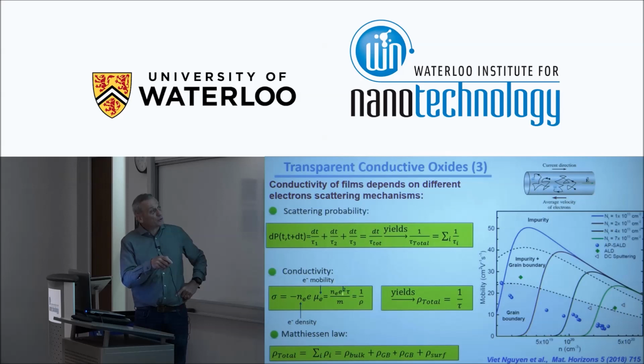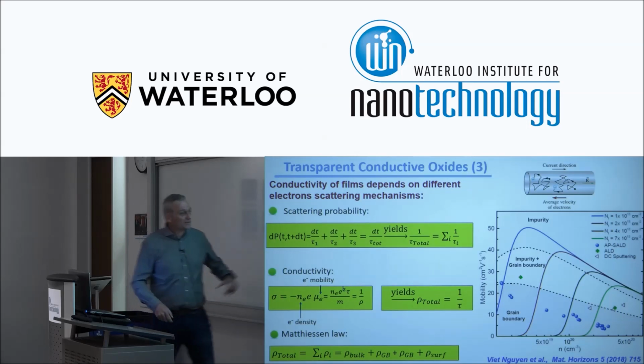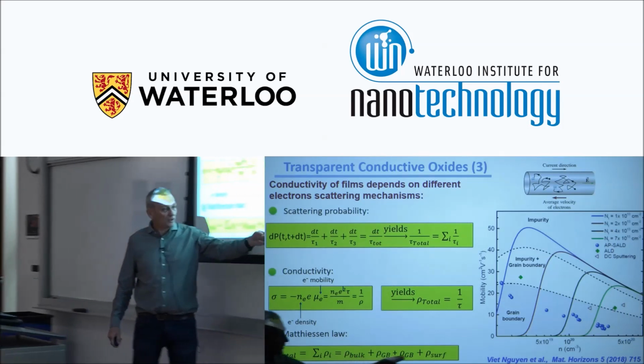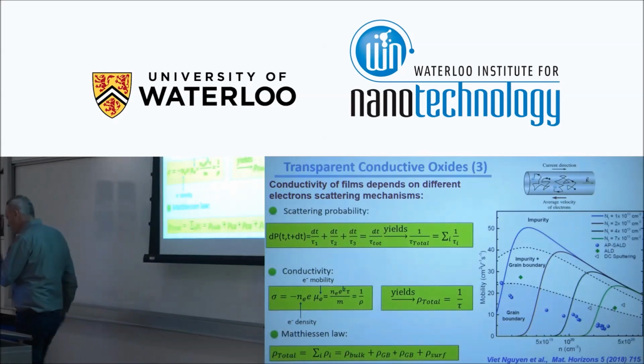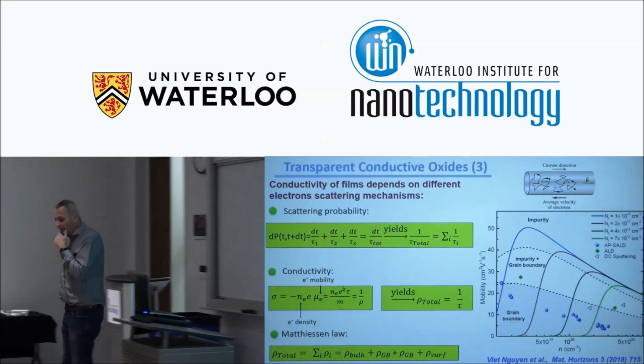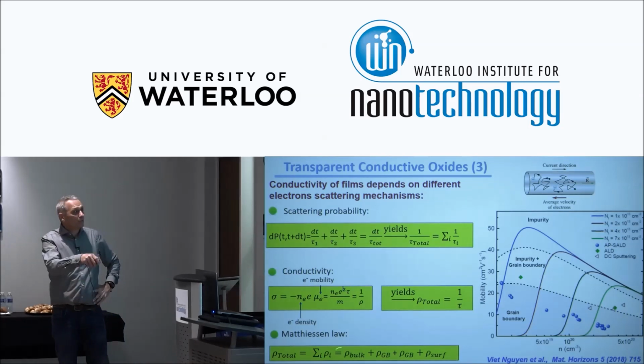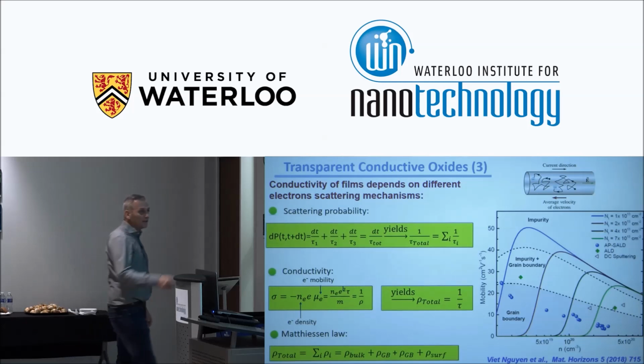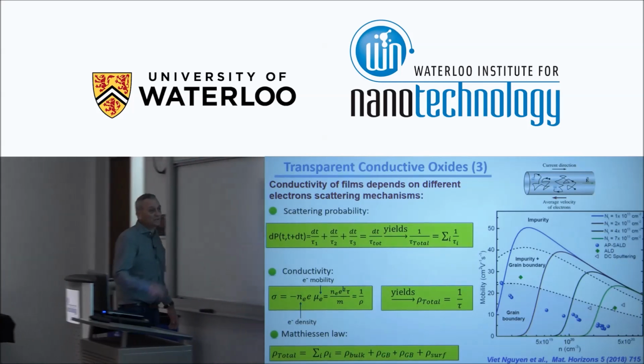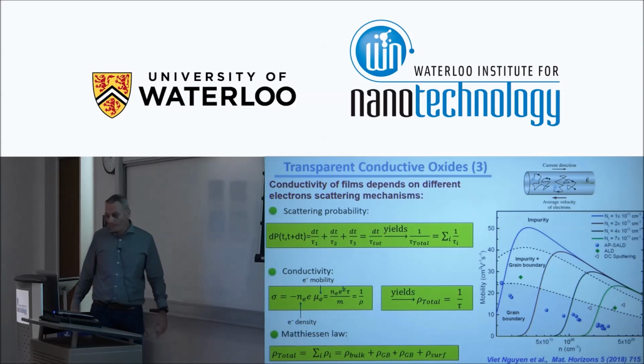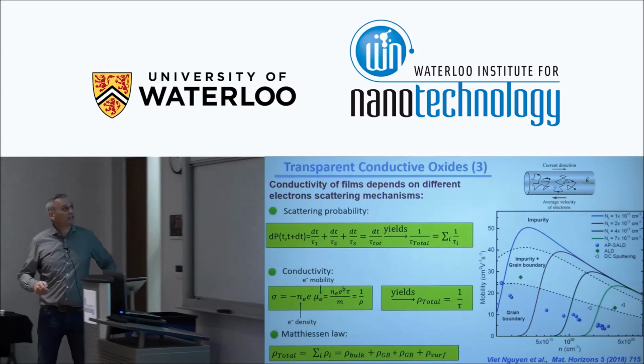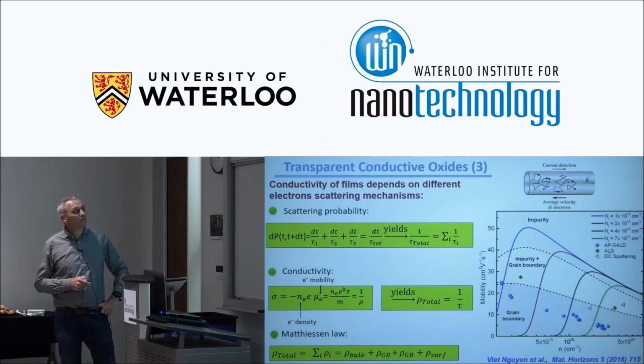And the conductivity, which is given by this for electrons, for example, is proportional to tau. That means resistivity is inversely proportional to tau. And that means we have to add the resistivities, saying that the total resistivity is just the sum of the resistivities associated to the different scattering mechanisms. And in the case of transparent conductive oxide, we have the bulk contribution, which is the phonons and impurities, for example, the grain boundaries, could be twins, and as well the lateral surfaces. So there is a lot of investigation to understand and to optimize the mobility.